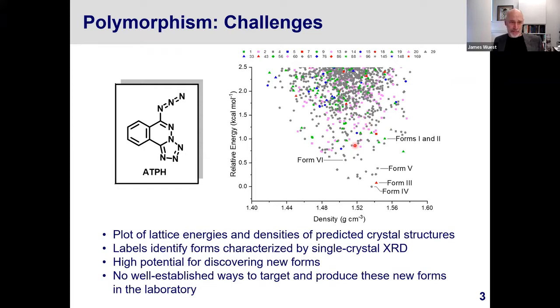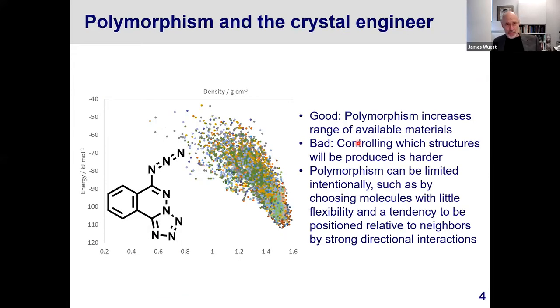Just to give you a little bit more of a sense of the nature of the challenge, between 0 and 1.7 kilocals per mole, so at this cutoff line, there are over 100 different polymorphic forms that are identified as potential structures. Even within 0.5 kilocals per mole down here, there are 12 potential structures, and nothing tells the experiments how to make these compounds in the laboratory. It's clearly an enormous challenge that remains, to a large extent, unmet.